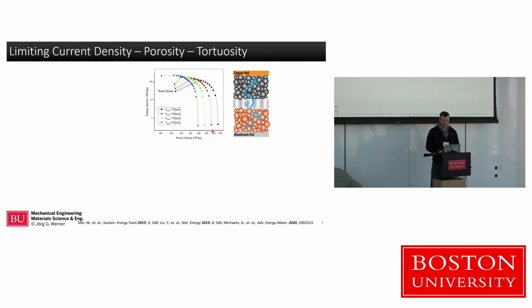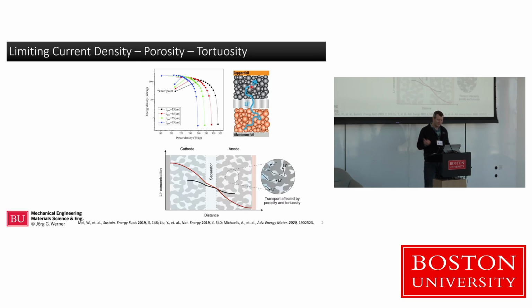However, you can also see that for the black one, the thinner electrode layers, you can run them at much higher powers to get the same amount of energy out of that system, or put the energy in during charging, versus the blue one that fails at much lower charging rates or power. And that has to do with how quickly these lithium ions can travel through your battery, right? Through the porosity that's between your materials. So if you look at it in a visual way, if you have a thin battery, think the current collectors are right here, you build up a concentration gradient while you're charging your battery from the cathode to the anode. The anode is the one in charging that takes up the lithium ions, so they get depleted from that pore space, from the electrolyte, during charging.